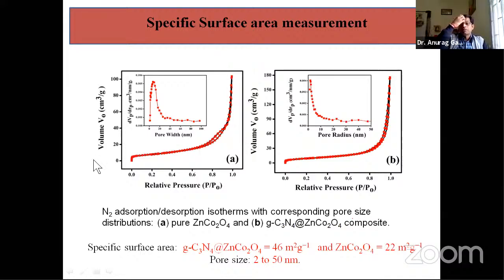So pore size is important in that sense. If the pore size is very small, less than 2 nanometers, then the electrolyte ions cannot enter the pores in sufficient numbers. And if it is very large, what happens? They will enter and immediately come out. Because of that, discharging time is affected. So we want the pore size to be in an optimized range, and this optimized range for energy storage devices is 2 to 50 nanometers. This 2 to 50 nanometer pore size range is good for these energy storage devices.